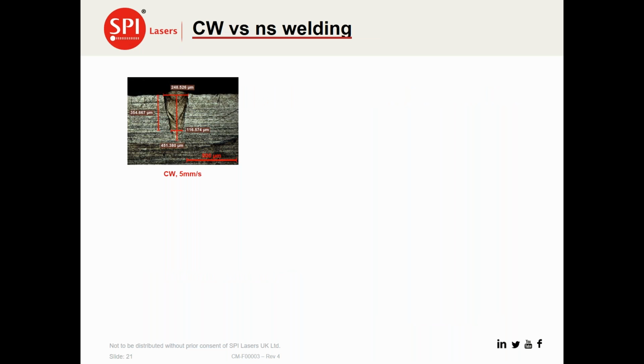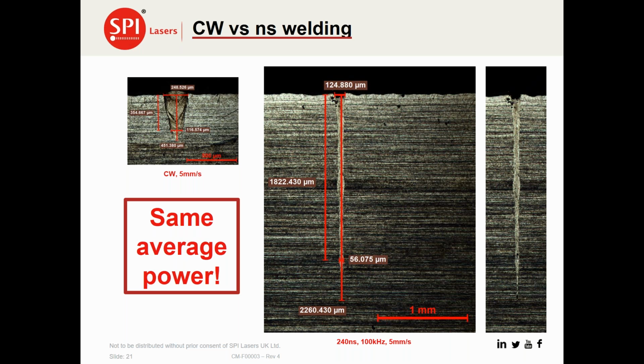If we now compare these to the nanosecond welding process, just to try to illustrate that it is very different here. This is a picture of a micro keyhole weld using a CW laser running at 5 millimeters per second weld speed. If we compare that to the new nanosecond process, we have a much different mechanism here. You can see that the nanosecond process is not characteristic at all of a normal CW weld, for example. It's much more like an electron beam weld in its cross section, which is shown here.